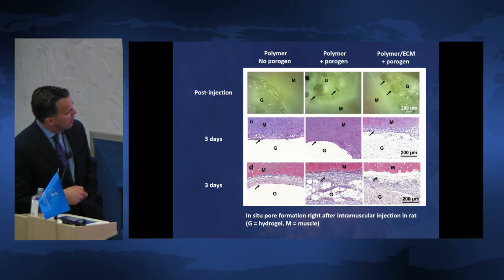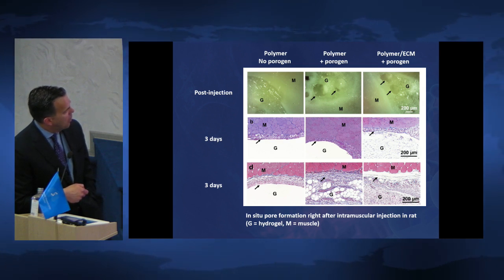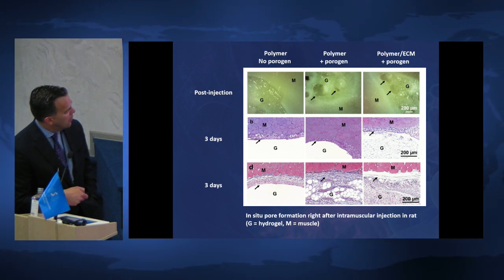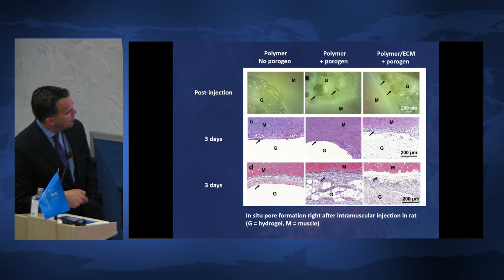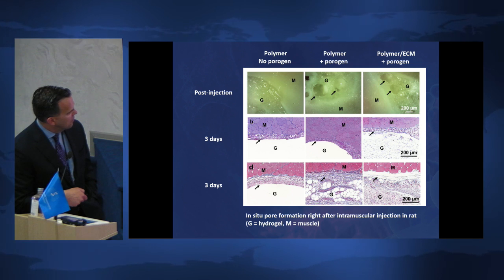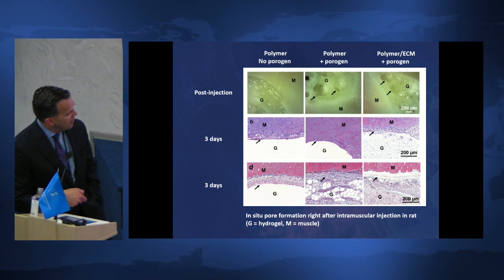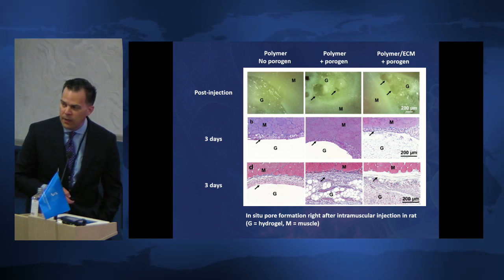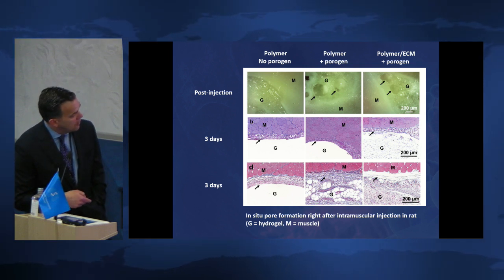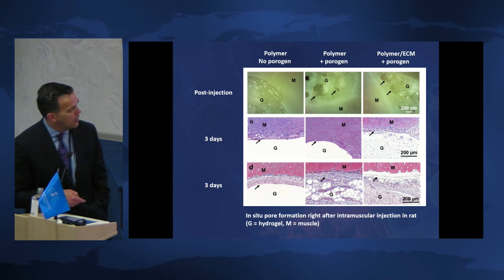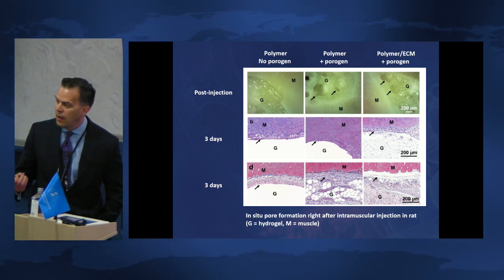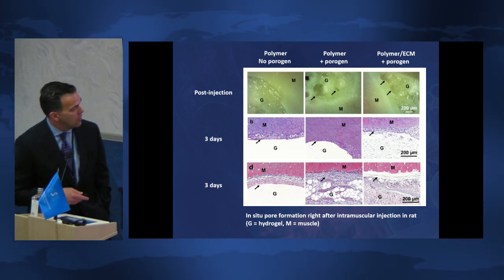You can see here the effect on the left. It's polymer with no porogen, which doesn't really do anything except give you a foreign body response around it. Polymer with the porogen, you get migration in, but you get a thicker capsule. That's not 3 days, actually. That's a typo. This is 8 weeks. So you get a foreign body capsule still. But when you have the porogen and the ECM, you get a very modest to no foreign body capsule. And we've been using this in adipose locations, showing that we can inject this and create volume and have very normal-looking adipocytes in that region.